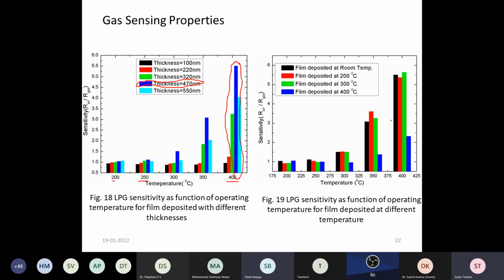If we see the films deposited at different temperatures, the sensitivity for the films deposited from room temperature up to 300 degrees centigrade is nearly the same. Why? Because when we are heating, crystallinity is improving, and sensitivity does not depend purely on porosity. It also depends on crystallinity, grain size, as well as porosity. So when we increase the substrate temperature, crystallinity and grain size increase, but porosity decreases. They complement each other, so there is not much variation. But at 400 degrees centigrade, porosity is drastically reduced. That's why we get a very low sensitivity for the film deposited at 400 degrees centigrade.